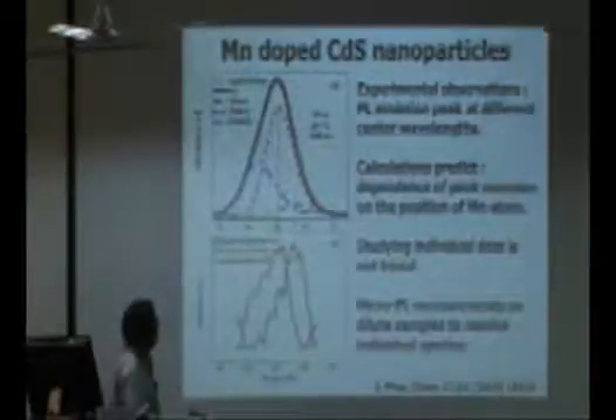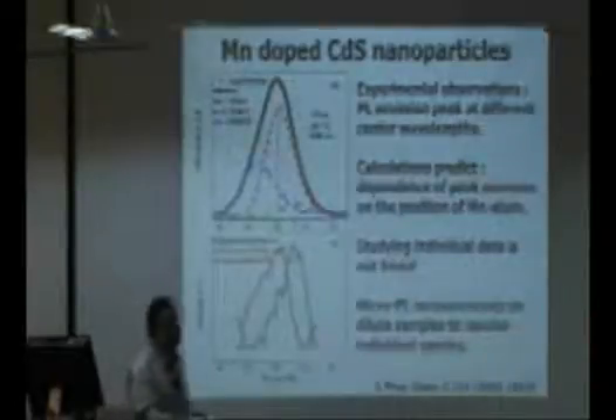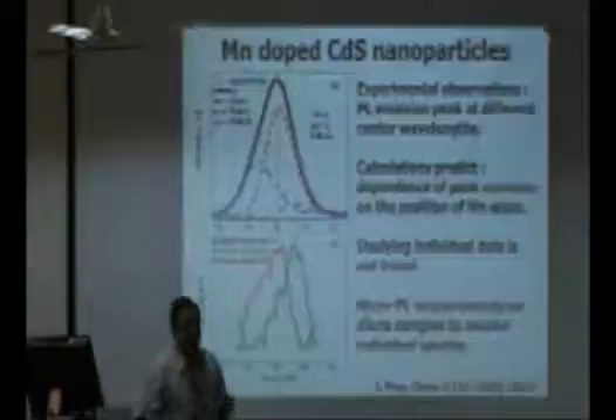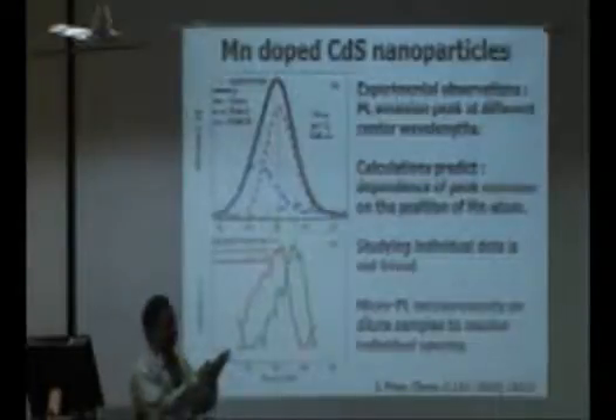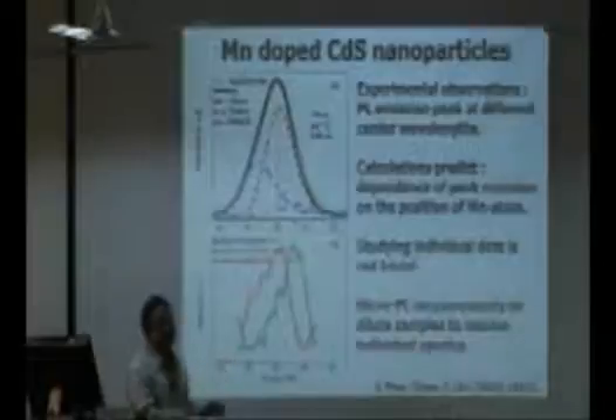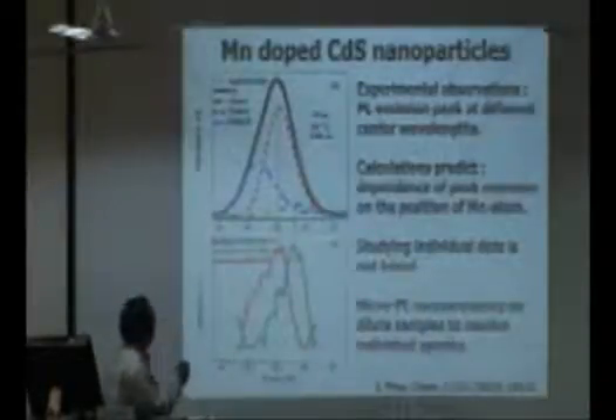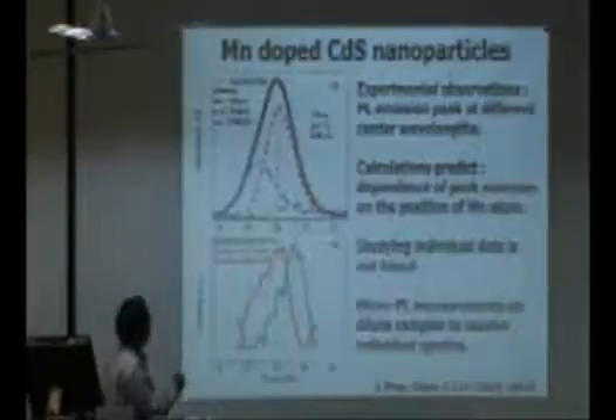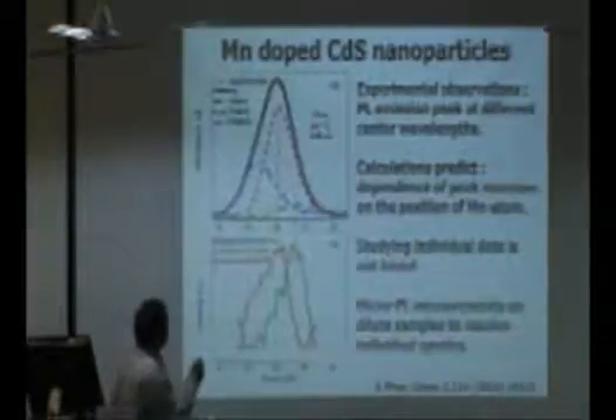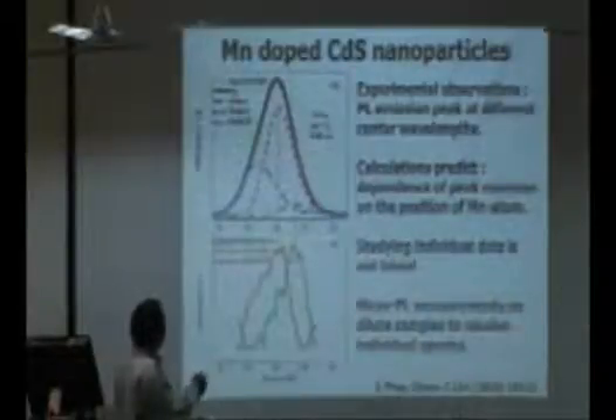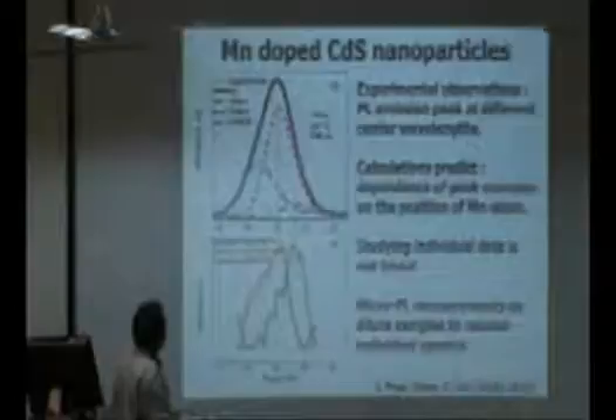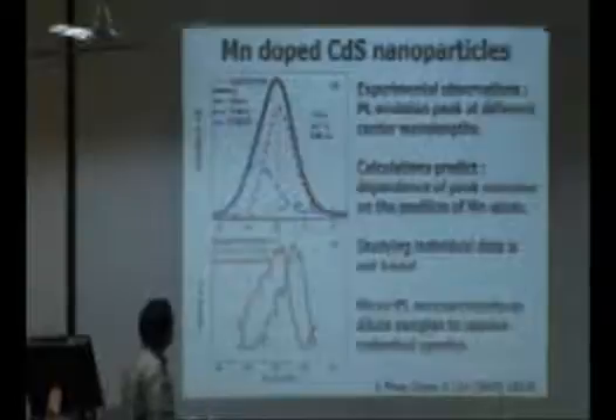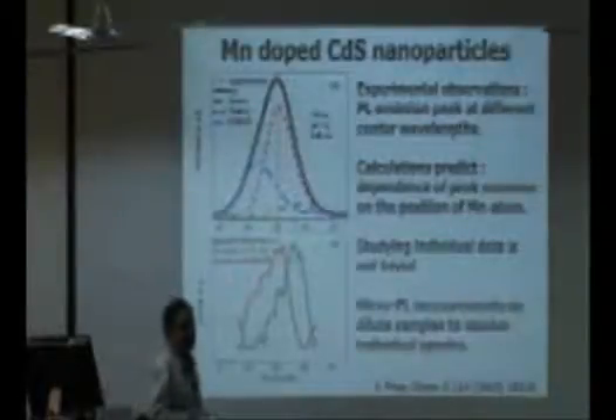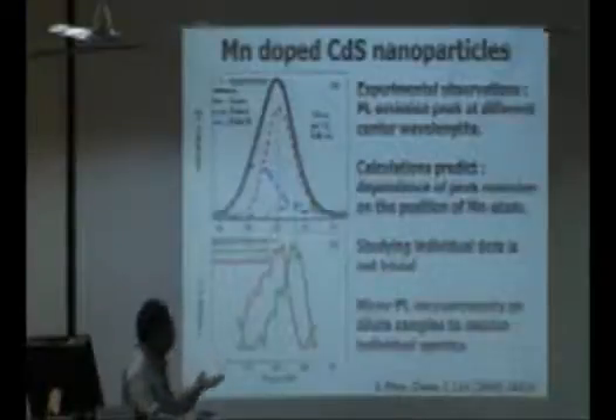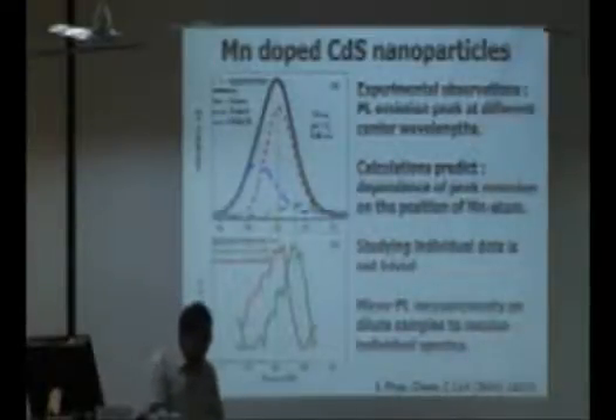What we found is that the position of the manganese atom inside the quantum dot is very important. For example, the manganese atom can be at the center, off center, or on the surface of the quantum dot, which results in different species. So 3 different species contribute to different levels and evolve into an ensemble peak. By resolving these single dot spectra, which matched well with the theoretical spectra, we showed that the position of the manganese atom is very important in deciding the center of the ensemble photoluminescence peak.